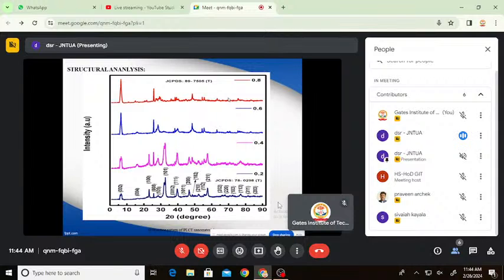So coming to the XRD analysis, this is the XRD pattern for the prepared PLCT nanoparticles. From the XRD pattern, it is confirmed that the reflection planes like 002, 004, 100, 008 up to 203 of PLCT nanoparticles are present with varying lanthanum content.